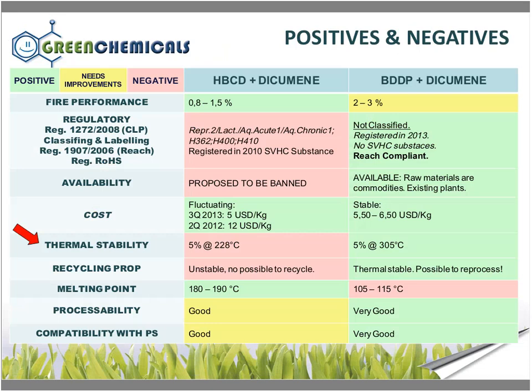One very good point of BDDP is thermal stability. Everybody of us knows how sensitive HBCD is to temperature. We know that when HBCD goes to 180, 190 degrees, it starts losing bromine and you get hydrobromic acid, and so corrosion and problems on the surface of the board come. So HBCD needs to be stabilized very well, but this is not the case for BDDP because it's really stable and it does not need any heat stabilization during the XPS process. So we try to make this the first good point of this solution.